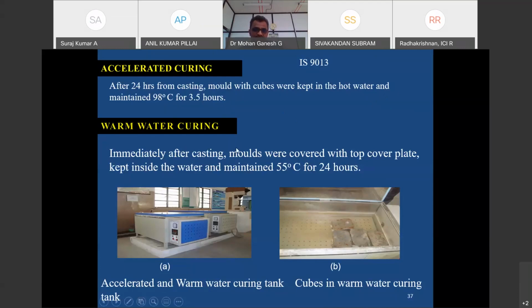The next process is warm water curing, which we do immediately after casting. The molds were covered with a top cover plate and kept in water, and we maintained 55 degrees centigrade for 24 hours. You see in this picture, top and bottom of the mold, it's fully covered, airtight, and we maintained that. The main purpose of these two alternate curing methods is that we can easily get the correlated 28-day compressive strength of the concrete. So we need not wait for 28 days. That is the main advantage of these two methods. The IS code recommends it, ASTM also recommends it. So we have done it for all our mixes.